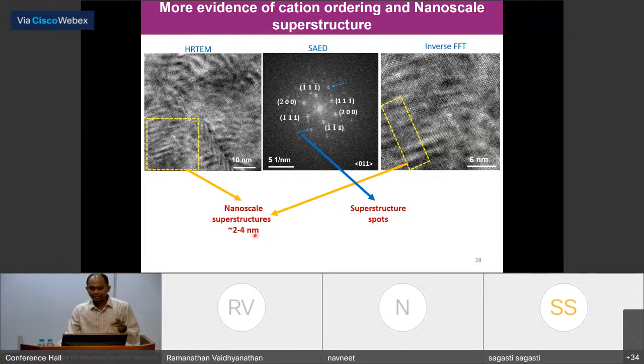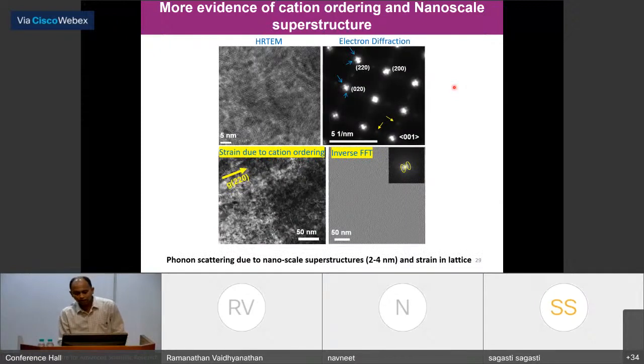And this domain actually forms by cation ordering, which we see by the cell doubling spots. And this is a more clear image. This is the inverse FFT image. So now I go to another part of the image. Here you can see this electron diffraction. There is a clear superstructure formation, the splitting of the fundamental spot in the fourth direction. So that tells that there is higher order nanostructure domain formation. And of course, there is a halfway weak spot that tells that this is basically cell doubling, which creates this nanostructuring domain. Okay.